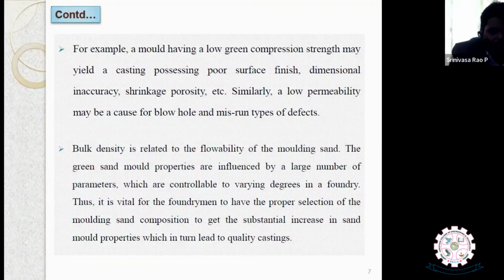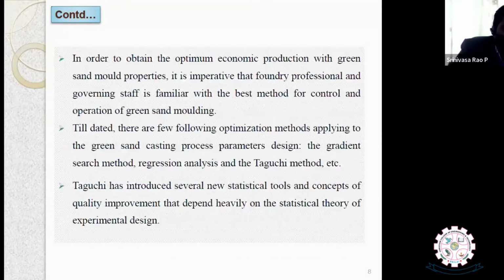And one more thing we can talk about is the bulk density, which is related to the flowability of the molding sand. In such a way, the green sand mold properties are influenced by a large number of parameters, which are controllable to varying degrees in our foundry. That is why a foundryman should be in a position to select the molding composition to get a substantial increase in sand mold properties, which in turn leads to quality castings. So quality castings depend upon the mold properties.